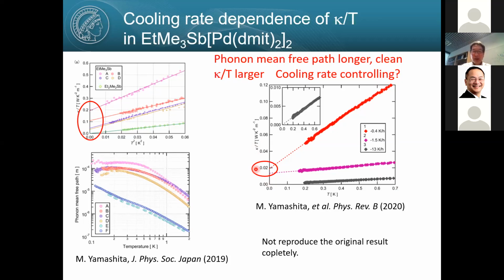Okay, but still, I have to admit, even in the slowly cooled sample, the magnitude of kappa over T is only 0.02, one order of magnitude smaller than the original report. So in that sense, the original report has not been completely reproduced yet. So this is a beautiful system, and it's likely we have a spinon Fermi surface, but there remain some experimental issues to pin down.